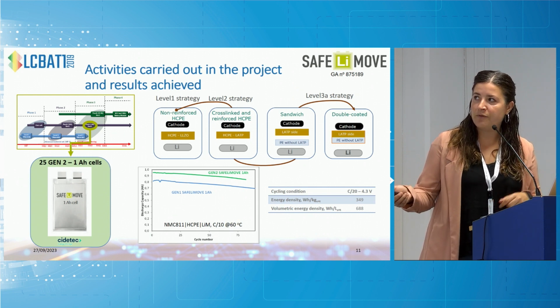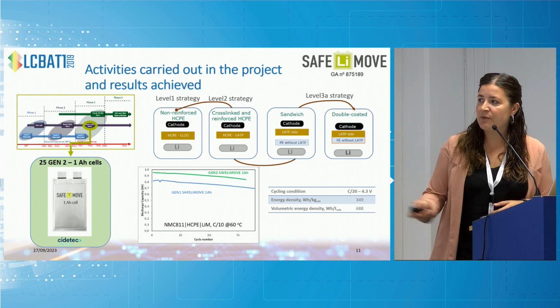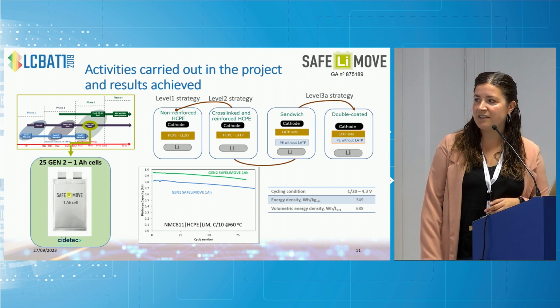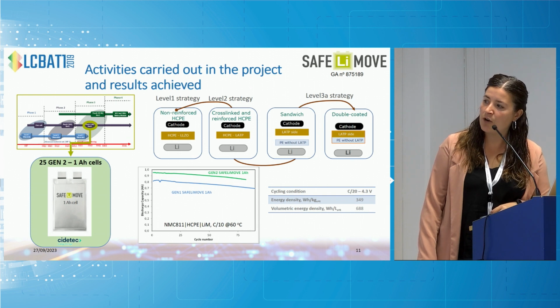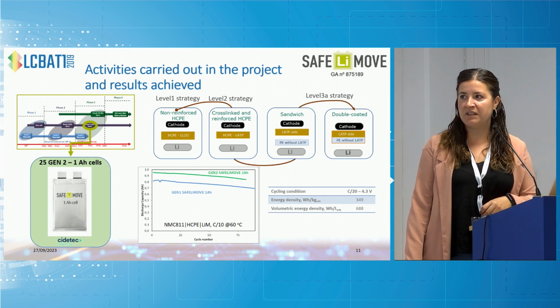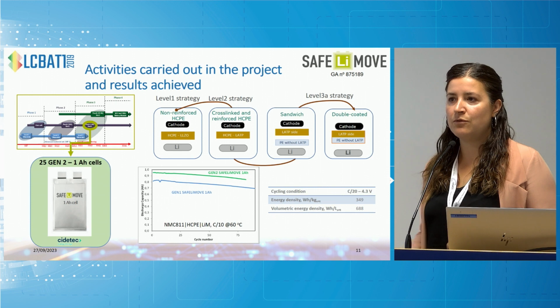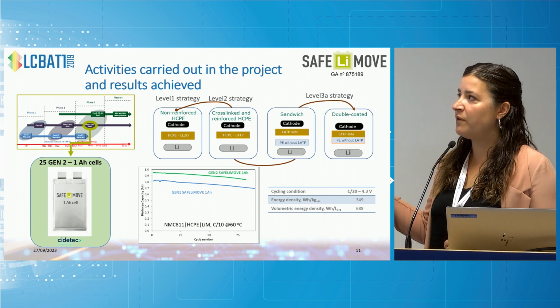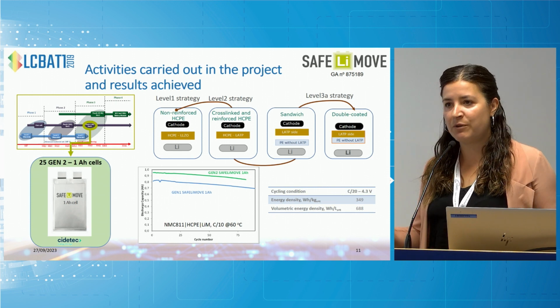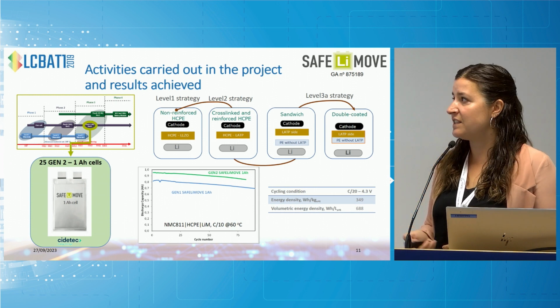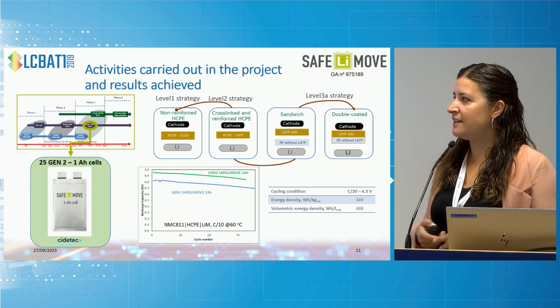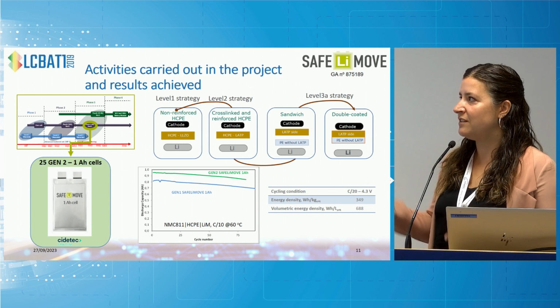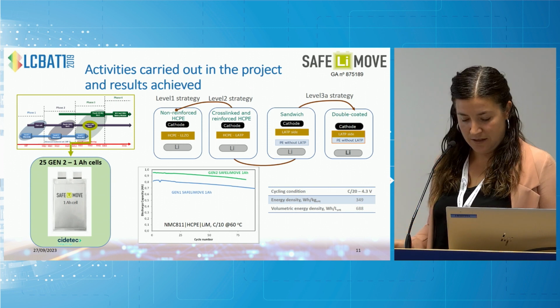And decreasing the thickness and increasing the active material content has allowed us to reach a higher energy density, both gravimetric and volumetric, in the range of 350 watt-hour per kg and close to 700 watt-hour per liter. Of course, there is still a lot to do in this regard. We really need to go further and understand the performance, the aging mechanisms, and the safety. But this is also one of the second main outcomes of the project.